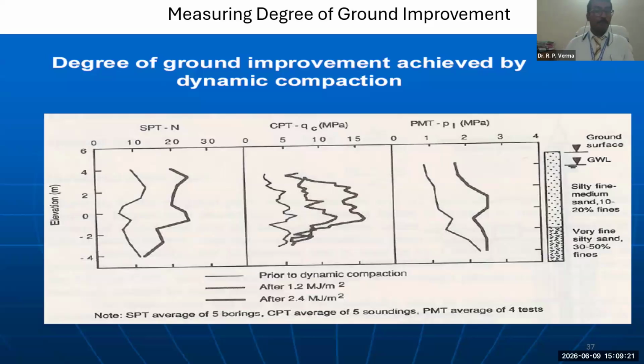To verify the success of dynamic compaction, we conduct extensive pre-treatment and post-treatment field tests. These case study overlays show standard penetration test N values, cone penetration test, tip resistance, and pressuremeter test results. Notice the substantial increase in soil properties after applying 1.2 and 2.4 megajoules per square meter of energy, validating the depth of improvement.